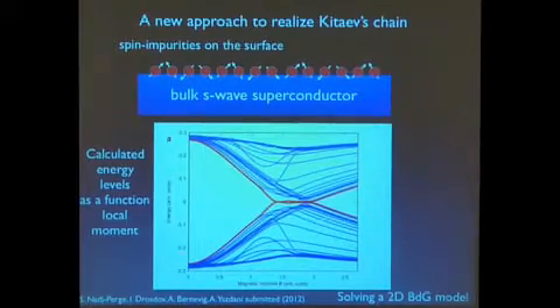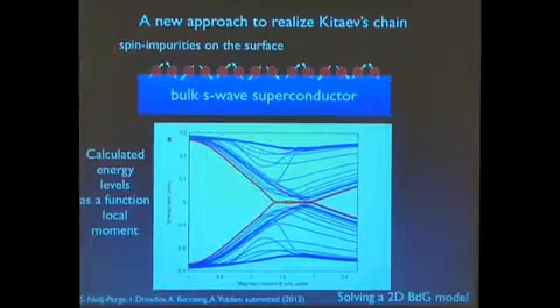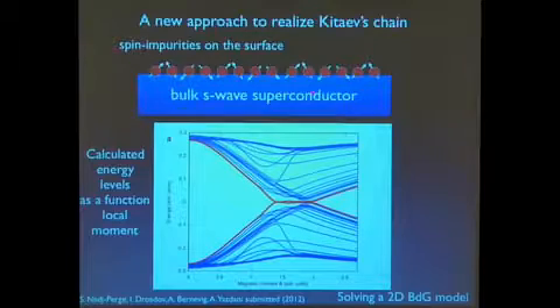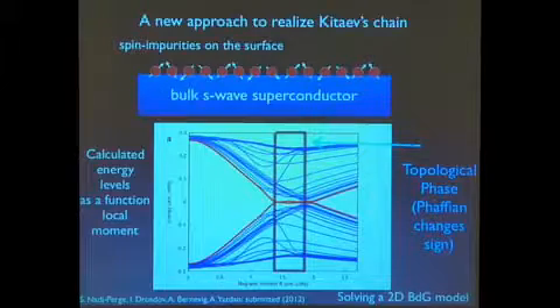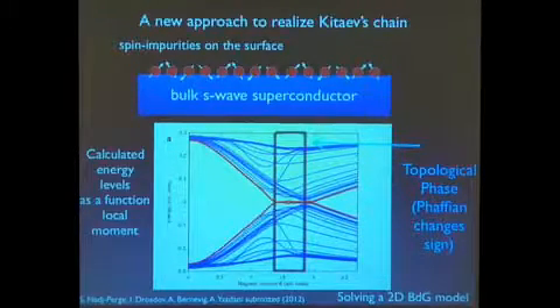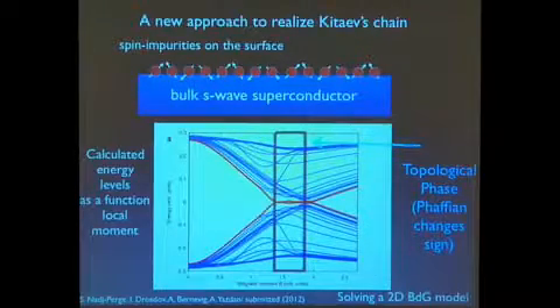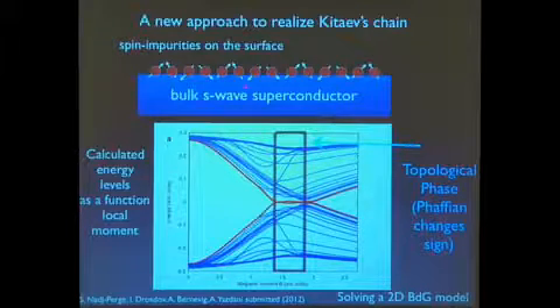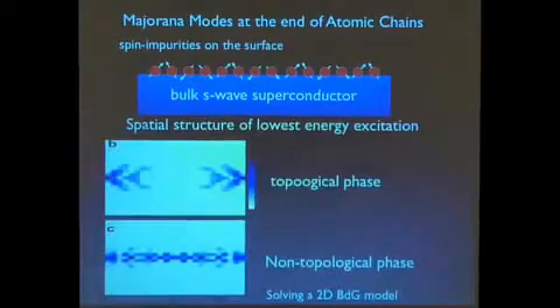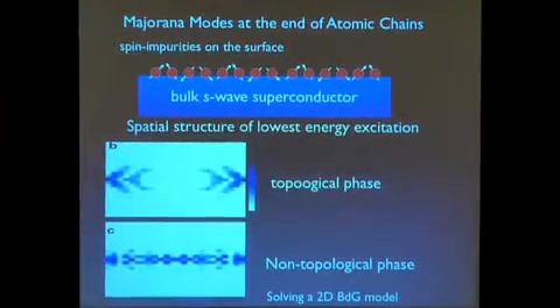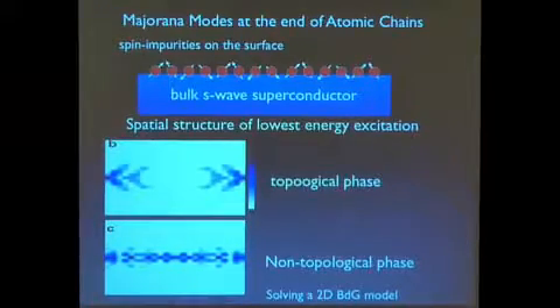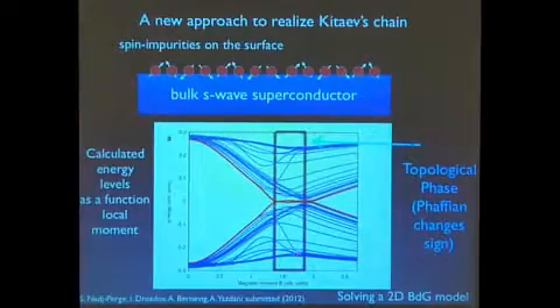And you find that if you look at the energy of the excitations in this system as a function of the strength of the magnetic interaction at each of these sites, as you turn up the exchange interaction, the first excited state comes down. At some point, you end up with states living at zero energy. This is where you get a topological superconductor. So this is a very, very simple problem. I just have a chain of magnetic atoms on the surface. I'm glossing over one detail having to do with the spin texture, which I'll get back to if you're interested. But what's interesting about this model is that it needs only something like 20 sites in which you can build this chain, and you can compute this when you're in this range of parameters.